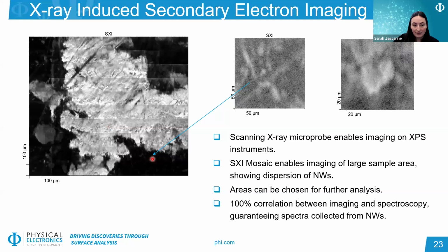But we can also use this to navigate to individual wires. So we can see a couple wire-like shapes, especially at the edges of these thicker powder clusters, we see this nanowire shape show up in certain areas, and this is one nanowire that's slightly bent. So in this case, we are using this imaging to find areas of interest, but because we have this microfocused X-ray beam, you can also collect data from individual wires, especially on the cobalt wires that were slightly bigger, and we could really detect individual ones with this imaging as well.